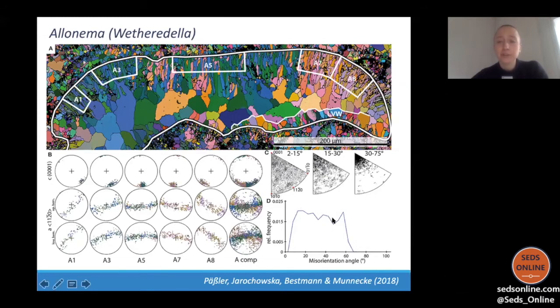There is a measure of order that is commonly used, which is the misorientation angle. So by how much are adjacent crystals rotated against each other. And the distribution of misorientations is something that is often used to express the crystallographic order. The misorientations go up to 60 degrees, but what we noticed is that the orientation of the misorientation axis is very constrained.